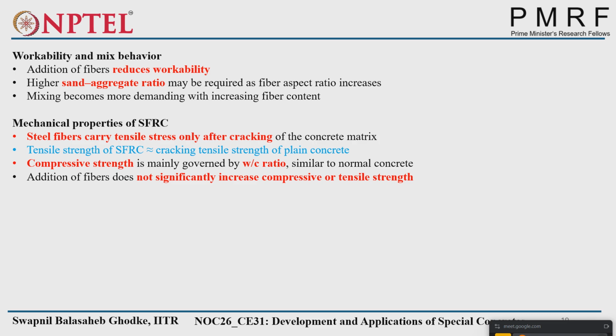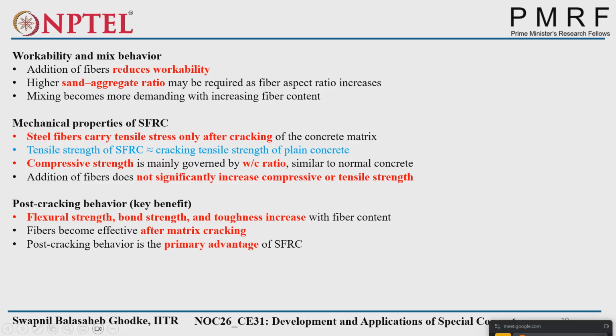So addition of fibers does not significantly increase the compressive or tensile strength. So what does it improve actually? It improves post cracking behavior, which is more important. We'll see with the plot also how it improves. Flexural strength, bond strength, and toughness increase with the fiber content.